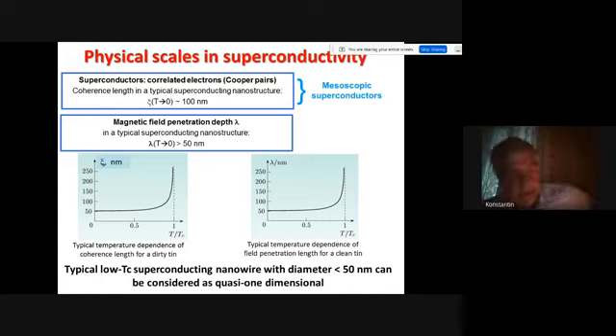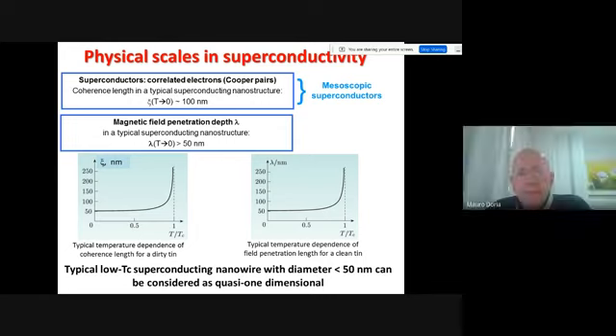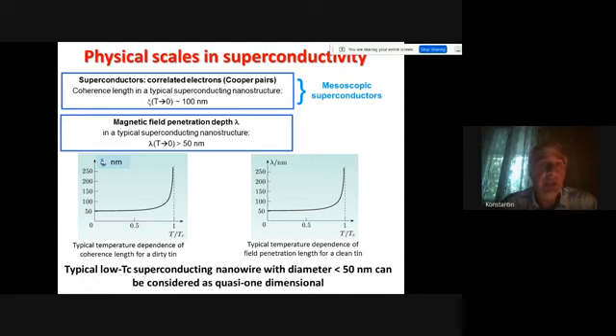Obviously, you are absolutely correct, but the short answer is that this is the subject of my next talk, because I really studied this effect in clean limit superconductors, where the thickness of a superconducting film is comparable to the mean free path. And there we do observe the quantum size effect, when the energy is quantized and the density of states is quantized. That's absolutely true. But in this work, we're mainly working with dirty superconductors, where the mean free path is at the level of 10, 20, 30 nanometers, and the cross-section of the wire is of the same order or larger. But there are no intergrain boundaries. So it's a polycrystalline structure, but relatively pure. And this effect is observed irrespective of the mean free path. It's a universal phenomenon. Okay, thank you very much.